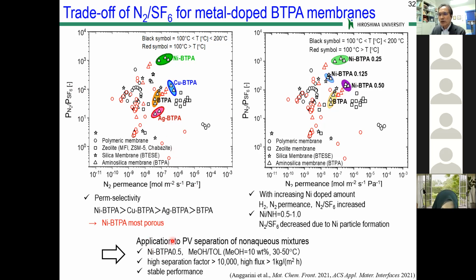So we believe this membrane has relatively large pores, and we apply these membranes to pervaporation separation of non-aqueous mixtures, such as methanol, toluene mixtures. We skipped the data today, but these membranes show a high separation factor, higher than 10,000, with high flux, and also very stable performance.